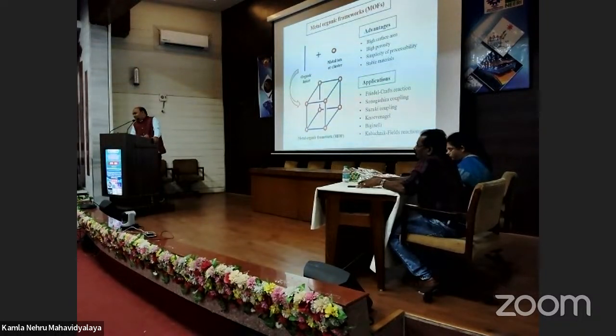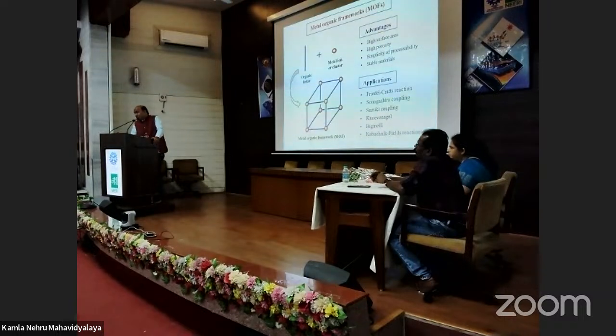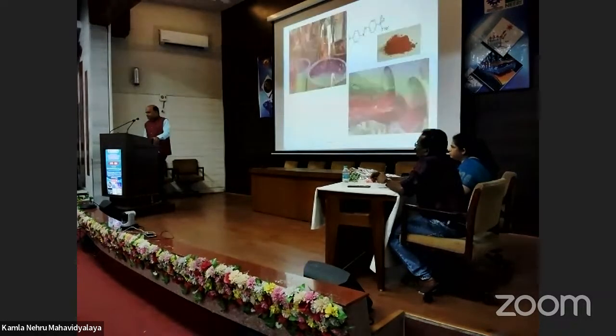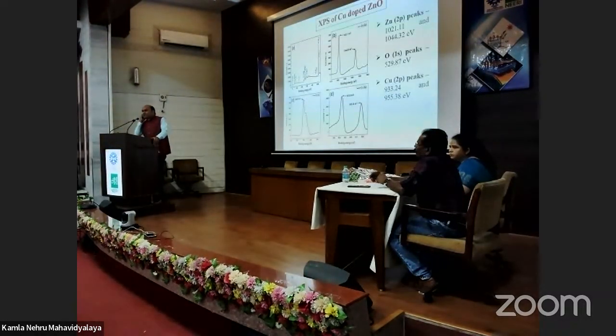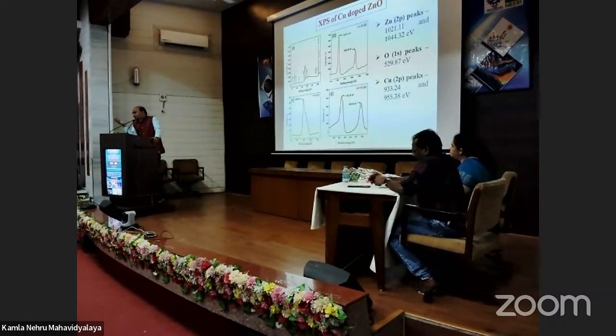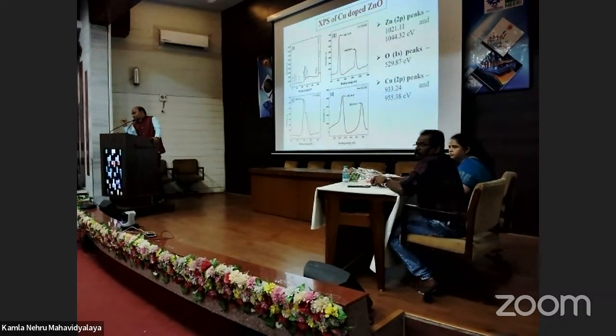One more interesting question is that we have newly fabricated this zinc oxide material. See, when we talk about the co-precipitation or sol-gel method, we need to provide an external device to control the temperature. Here we can control the temperature as well as change the morphology in the case of the hydrothermal method. By varying the temperature, we can get a good morphology with respect to the temperature, and that's what we have done.